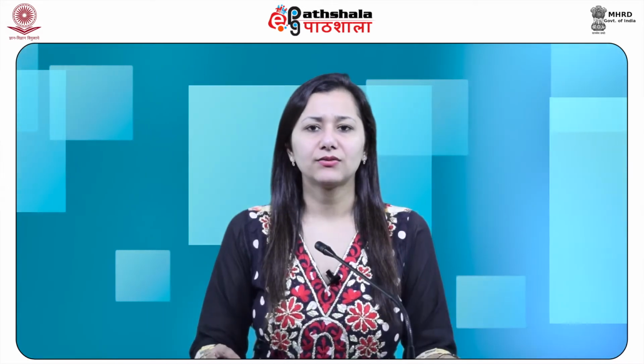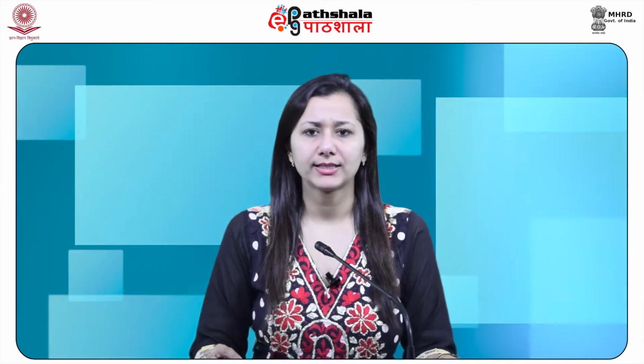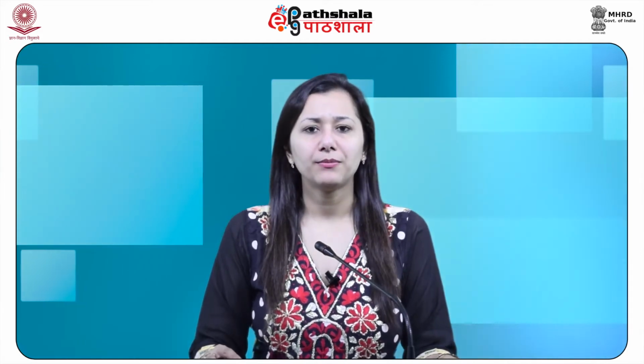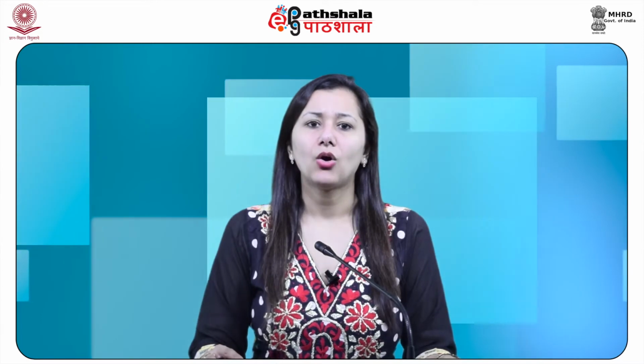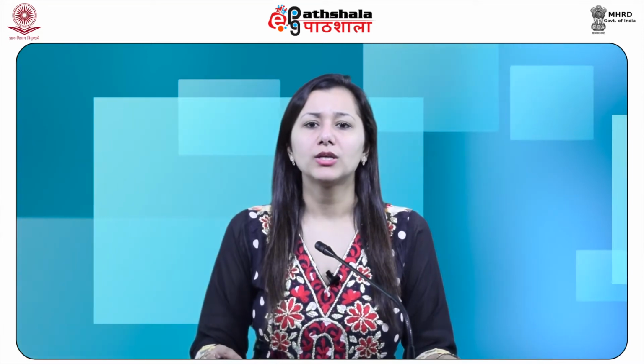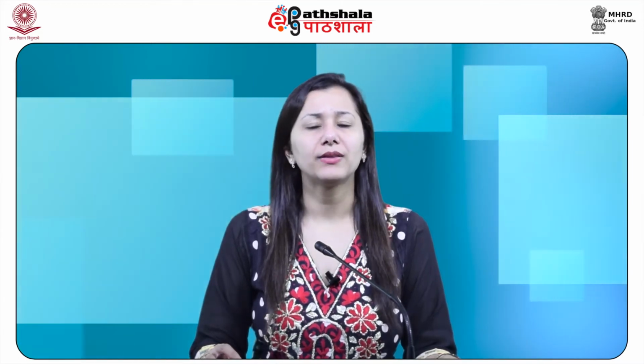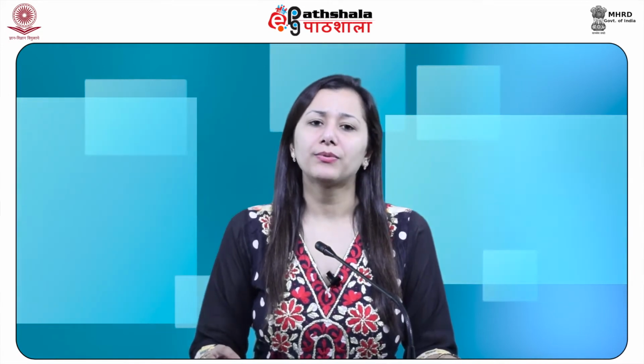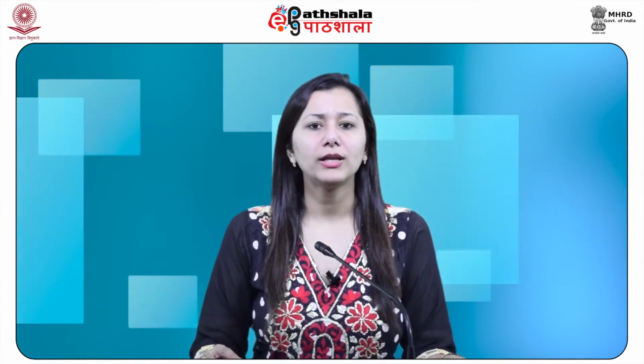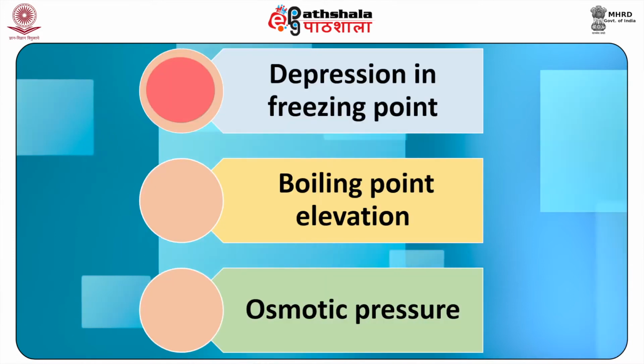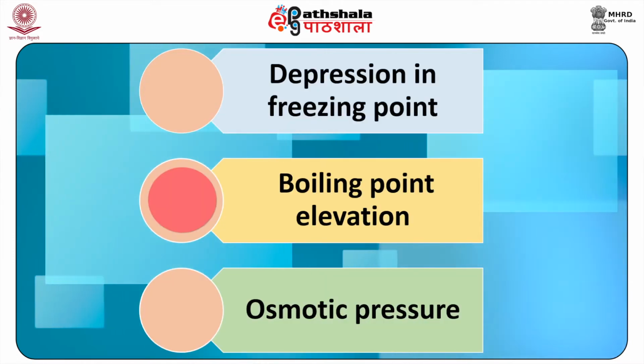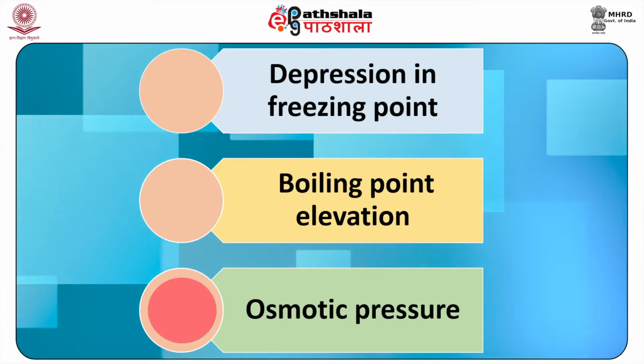Analytical techniques for the determination of molecular weights can be classified into primary and secondary techniques on the basis of whether or not standards are needed to calibrate the instrument. Most of the primary techniques are based on the colligative properties such as depression in freezing point, boiling point elevation, and osmotic pressure.